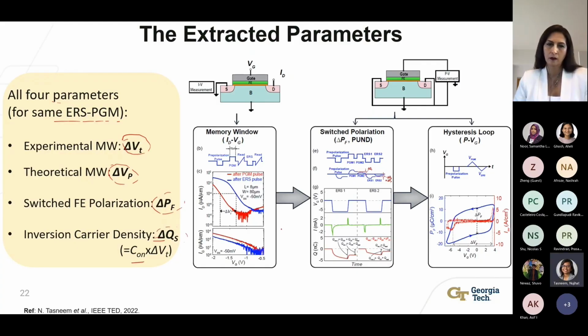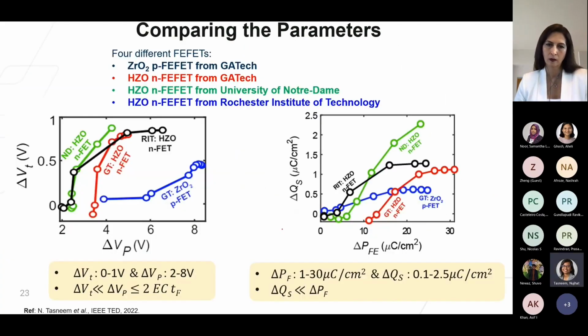So we did this experiment on 4 different FeFETs, a zirconium oxide P-type FeFET and 3 HZO N-type FeFETs fabricated in 3 different facilities. So we extracted the 4 parameters from all 4 of these devices and compared them with one another, shown by these figures over here. The first figure shows that the experimental memory window delta VT for all 4 of the devices is limited to 1 volt, which is very low.